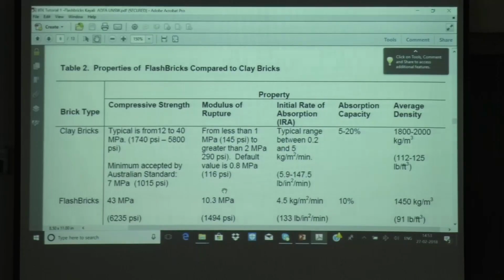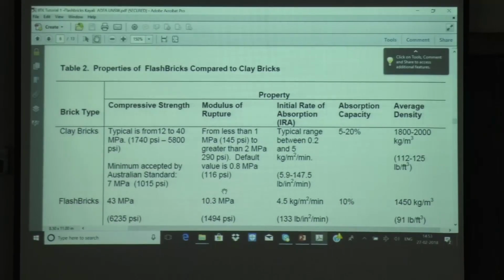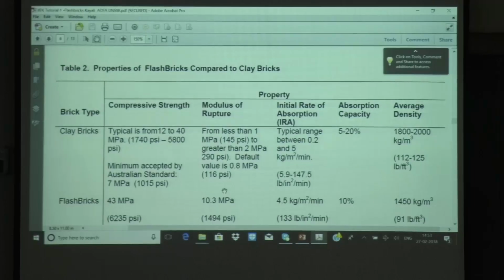Okay. Modulus of rupture means when you break it, like Dr. Kamalkar yesterday showed all those graphs. Modulus of rupture is that angle and also the upper limit. So it can be from less than 1 MPa to greater than 2 MPa. So it's not very high. Initial rate of absorption for clay bricks is typically between 0.2 and 5 kg per meter square per minute. Absorption capacity is 5 to 20%, and average density is 1800 to 2000 kg per meter cube, which is about, I would say, 2 grams per cc.